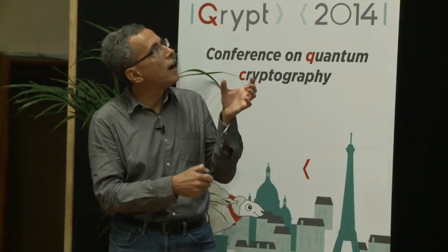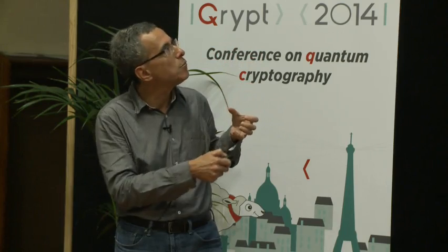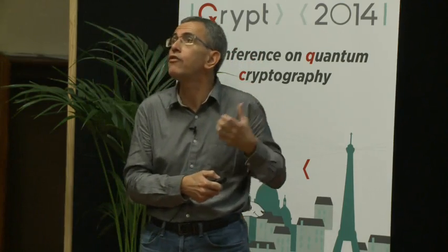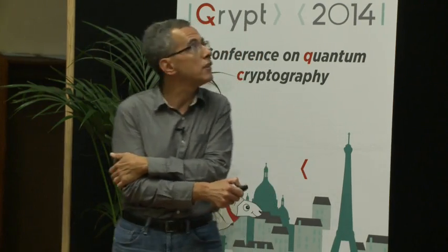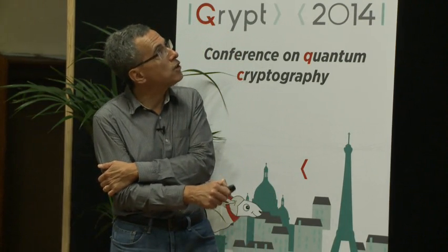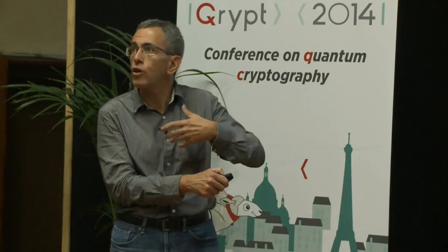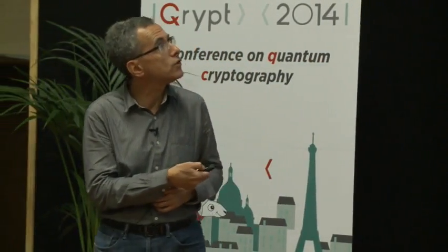So in our case, this chunk is really about a millimeter in size, but it can in principle be made down to pillars a few microns in diameter, which are fabricated at LPN near Paris in terms of the state-of-the-art pillars. So it's a bunch of semiconductor layers for manipulating the photons, as well as having an electron-doped layer to inject electrons, and you insert everything inside either a liquid helium bath cryostat or a cryogen-free cryostat, as I alluded to in the beginning of the talk.